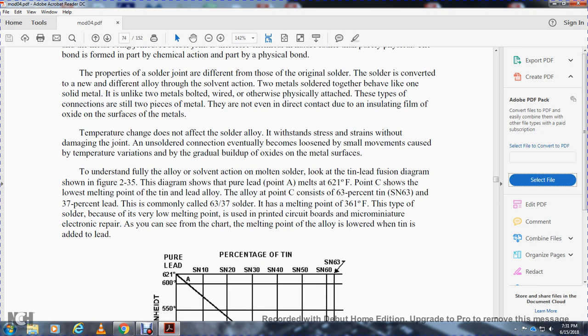To understand the full alloy solvent action of molten solder, look at the tin-lead fusion diagram in figure 235. The diagram shows that pure lead, point A, melts at 621 degrees. Point C shows the lowest melting point of the tin-lead alloy. The alloy at point C is 63% tin, SN63, and 37% lead. This is commonly called 63/37 solder. Its melting point is 361 degrees Fahrenheit.